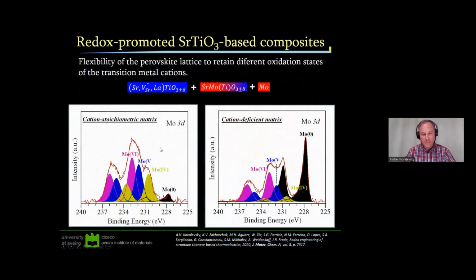By XPS we confirmed that indeed we have a mixture of different molybdenum oxidation states. So we have part reduced to metallic nanoparticles, and we also have part which still retains in the flexible perovskite lattice. If you would put just molybdenum oxide under the same reducing conditions, it would reduce completely to metallic molybdenum. This is not happening in this case because the perovskite lattice allows us to retain part of these molybdenum cations in oxidation states higher than zero.